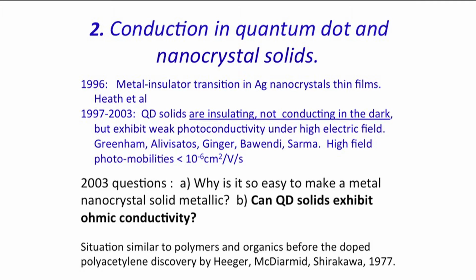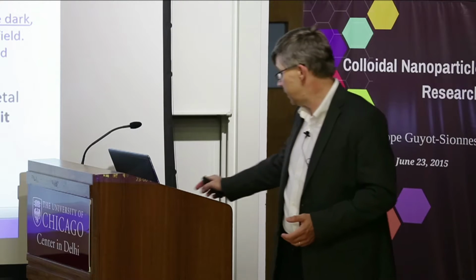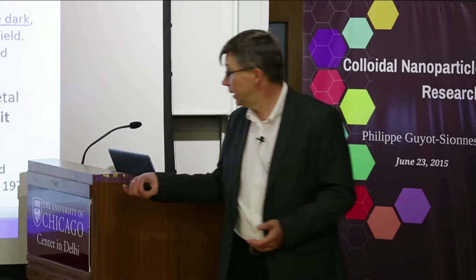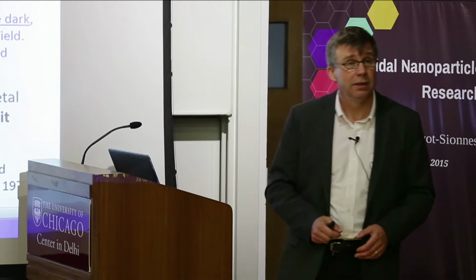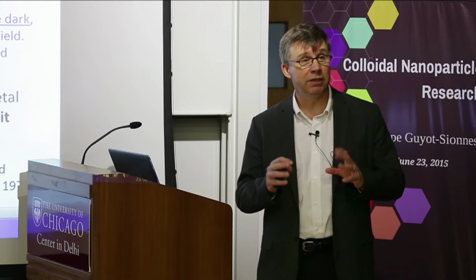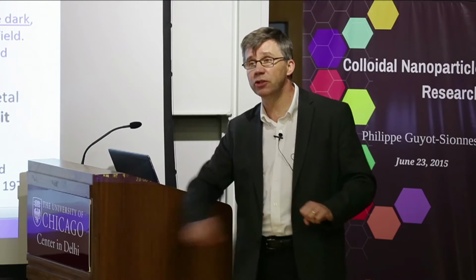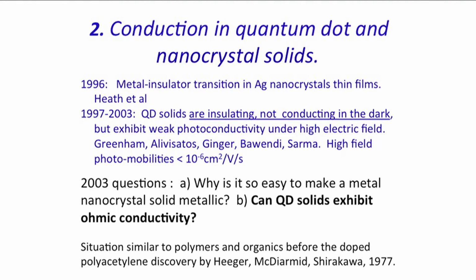But then it led people to believe that quantum dots would also show this kind of metallic conductivity quite easily. But the fact is, for the next 5 or 6 years, quantum dot solids were only extremely insulating. And one could observe some sort of current going through, but only when photoexcited and under very high electric field, which is a situation very similar to the situation that organics faced before the work of Heeger, MacDiarmid, and Shirakawa. In other words, organics were the same. You could observe conductivity, but you had to apply such a high field to pull the charges through. And you had to photoexcite the system also.